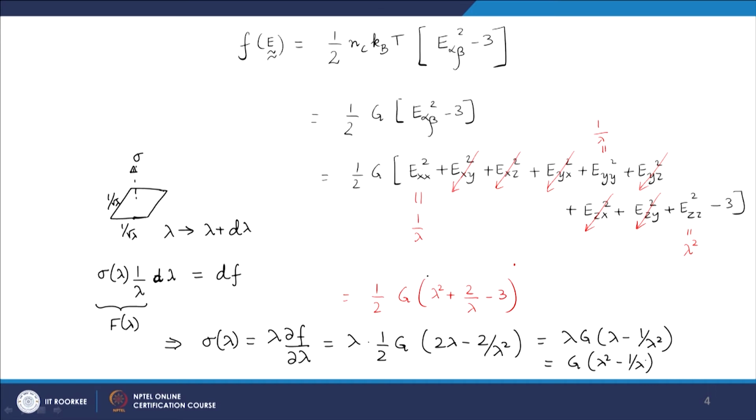Okay. So, now there is a bit of a problem in this equation, since we assume that the free energy varies like the energy of an ideal chain, there is no term in this equation that will prevent the stretching of chain to unphysically high values. But in reality, if I stretch the polymer network, there will be a moment where all the strands are stretched to the maximum possible contour length, and beyond which there can be no extension.